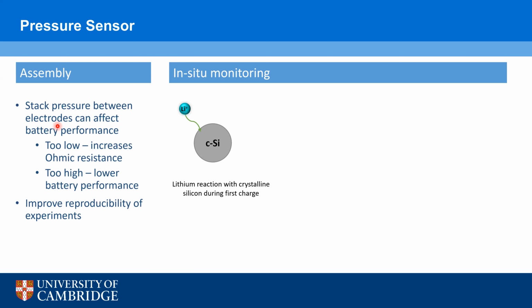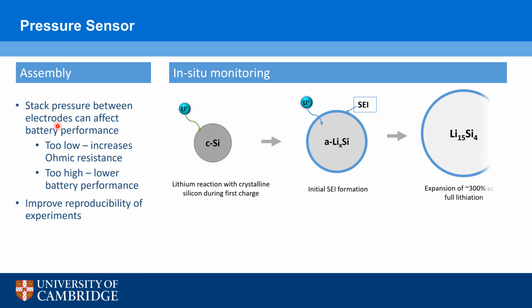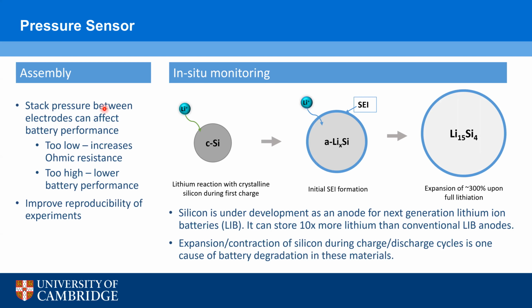And the other thing we propose to do is to do some in situ monitoring. So I'll go through this with an example of a material that has quite some interest in research at the moment, which is silicon. Silicon is expected to be the next anode material in next generation lithium-ion batteries, because it can store 10 times more lithium than conventional anode materials, meaning we can increase the energy density of lithium-ion batteries using this material. However, it's not without its issues.